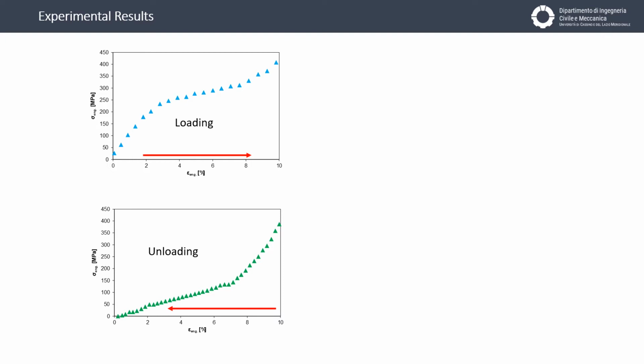Then we have the third stage characterized by the slope of the martensite. In the loading condition, you can see the third stage is wider than the first one, and then we have a different second stage where we have a transformation of martensite into austenite. It's a reverse transformation, and then the first stage is very short here, characterized by the recovery of elastic energy of the austenite.